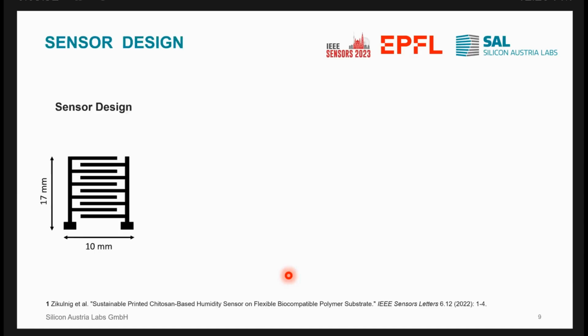For the presented sensor, we present two different sensor designs. This one is referred to as sensor 1 in the following. And here we just see a classical interdigitated structure. And between those LIG electrodes, we have the Chitosan layer. So as a very simplified equivalent circuit, you can say that the whole sensor system, if you consider it as a serial resistance, you see this as the LIG, first R, and the resistance of the Chitosan